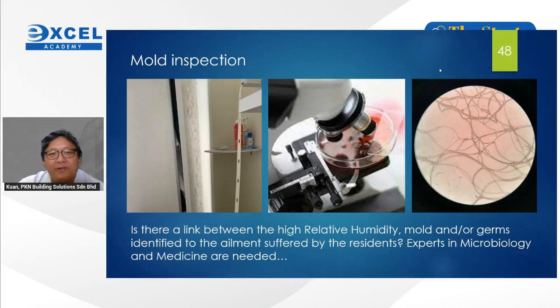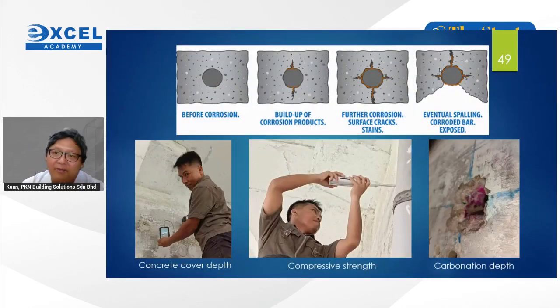Okay. So for the concrete, when it is exposed to the dampness, especially in the presence of chloride, for instance, building close to the coastal area, as well as building with swimming pool, the chloride is an accelerator, or the catalyst, that can accelerate the corrosion process. So firstly, we need to check the design parameter. This is actually a swimming pool. Okay, firstly, we check the design parameter, concrete cover depth using a cover meter.